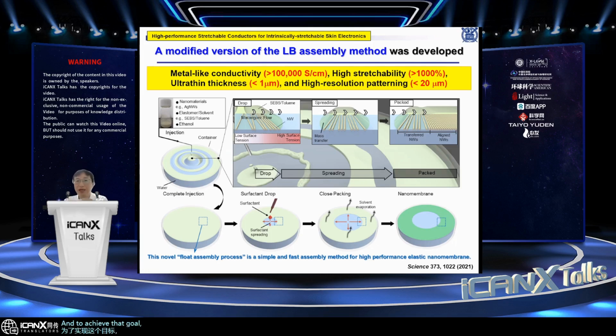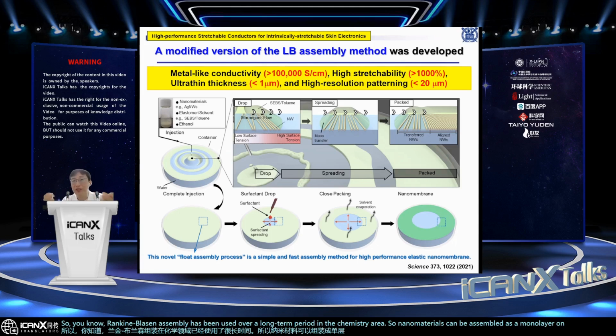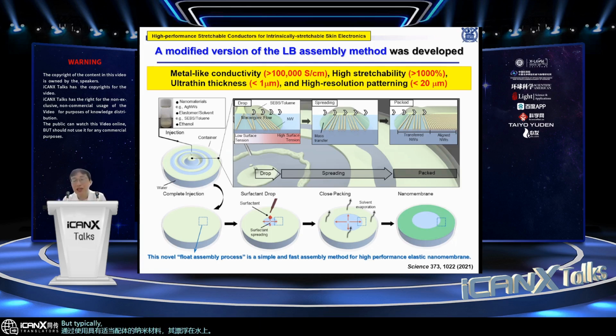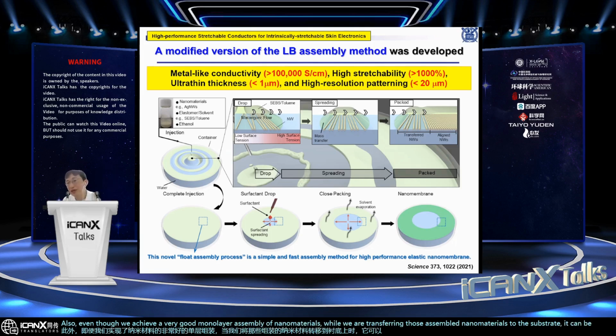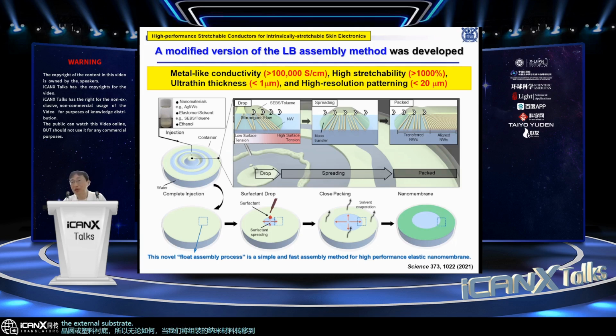And to achieve that goal, we developed a new material, an ultra-thin nanomembrane, by using a modified version of the Langmuir-Blodgett assembly method. Langmuir-Blodgett assembly has been used over a long period in the chemistry area. Nanomaterials with appropriate ligands can be assembled as a monolayer floating on the water surface. But typically, the Langmuir-Blodgett assembly process takes a long time. It's very slow. Also, even though we achieve a very good monolayer assembly of nanomaterial, while we are transferring those assembled nanomaterials to the substrate, which can be a wafer or plastic substrate, the assembly can be easily broken.